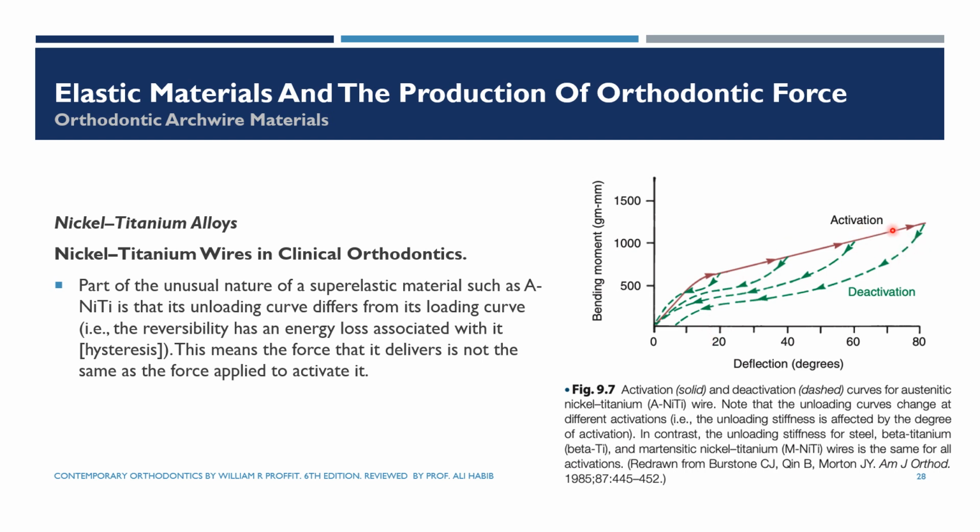So if you activate the wire up to 80 here, you can see that the amount needed to load the wire on the bracket was more than 1000 gram-millimeter of moment. And then with time, the force quickly decreases and becomes less and less until it goes back to 0.